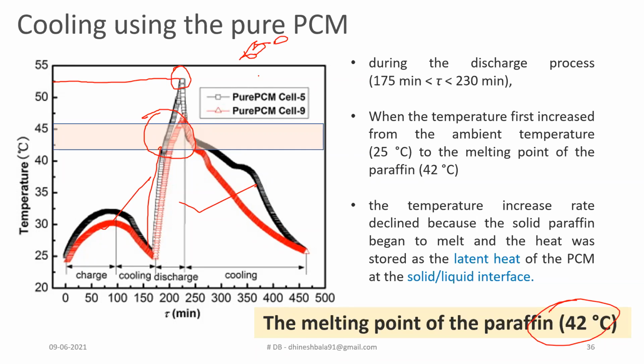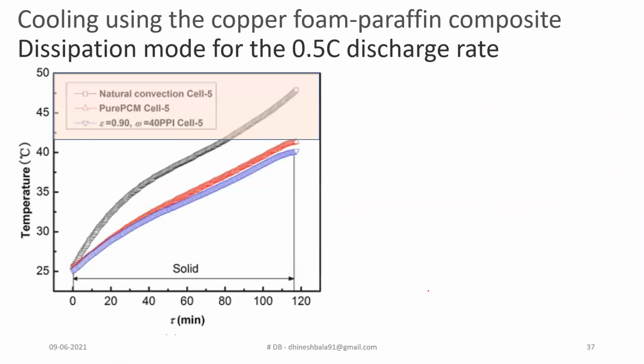So during the discharge, especially for the time of 175 minutes to 230 minutes, when the temperature first increased from the ambient of 25 to the melting point of 42 degrees Celsius, the temperature increase rate declined because the solid paraffin wax began to melt, and the heat stored as the latent heat of the PCM is effectively used for the conversion of solid to liquid interface. And next, by making use of a copper metal foam. So in the previous case, the maximum temperature rise of 52 degrees Celsius.